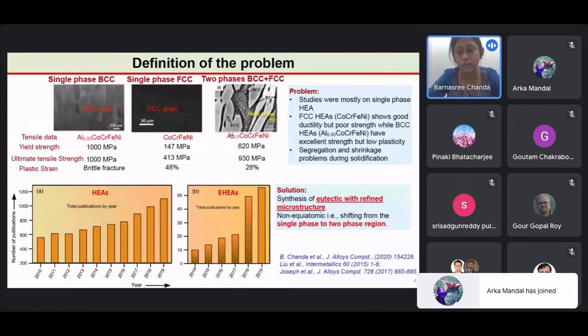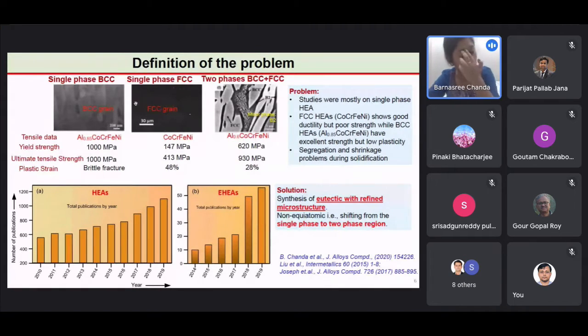At that time, most of the studies were on single phase high entropy alloys. But single phase BCC, although it has high yield strength, comes at the cost of limited plastic strain. Contrary to this, single phase FCC has high plasticity, but at the cost of limited yield strength. Therefore, we have concentrated on the eutectic high entropy alloys.